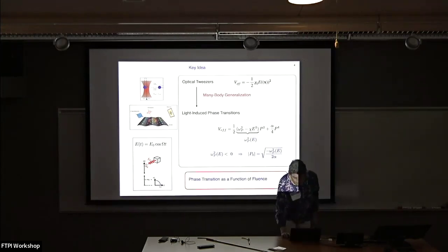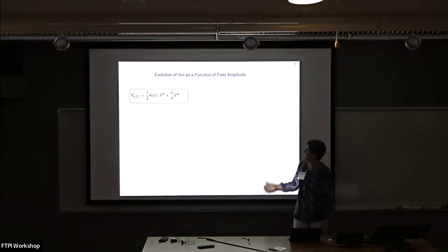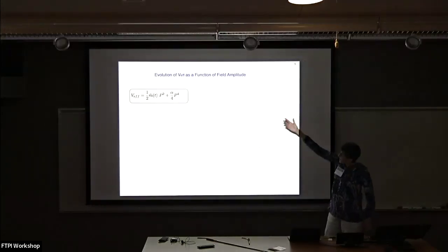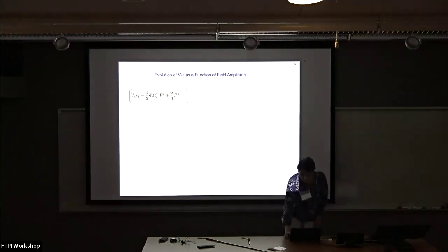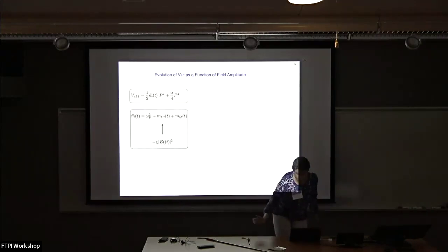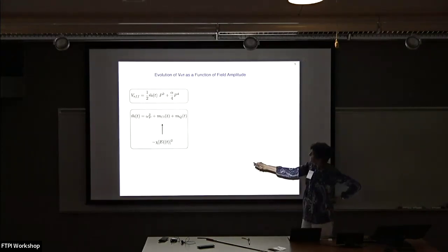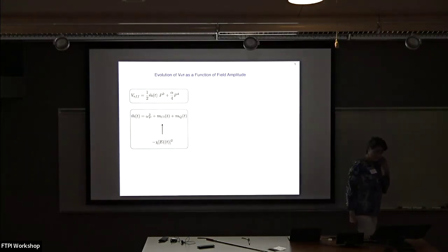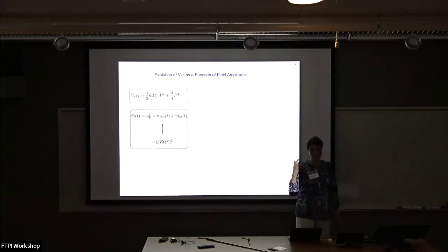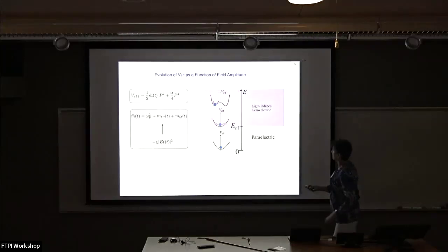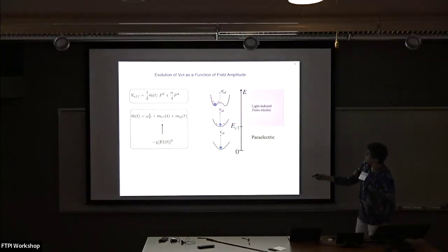And then we have a phase transition as a function of fluence. Let's just get a sense of how that works. We have an effective potential that has a renormalized mass term plus a P to the fourth. P is just our order parameter here. Now here's the polarization. This is the bare mass. This is a classical contribution due to the anharmonic coupling that gives us this minus chi E squared. And then you can even ask about quantum fluctuations, which of course should act in the other direction. And what you end up with is phase diagrams, because paraelectric, then you have a softening into a light-induced ferroelectric phase.